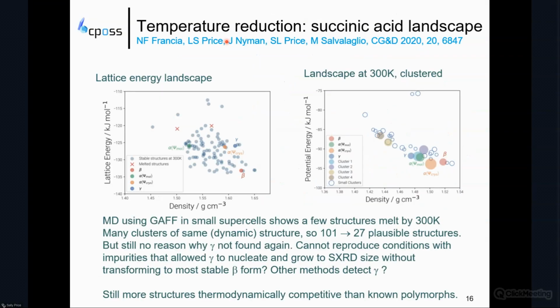We applied this temperature reduction. So this shows the minima, the lattice energy using the GAFF force field, and within that force field, a few of the structures melted. And then by doing the 300K clustering, there was a lot of amalgamation. The size of the sphere tells you how many of the structures coalesce to those structures. And so we reduced 101 to 27 plausible structures. Still an overprediction